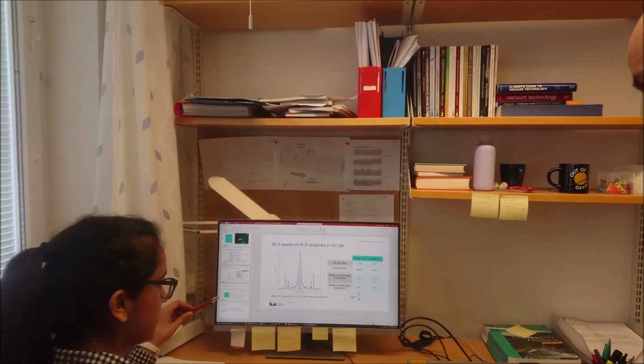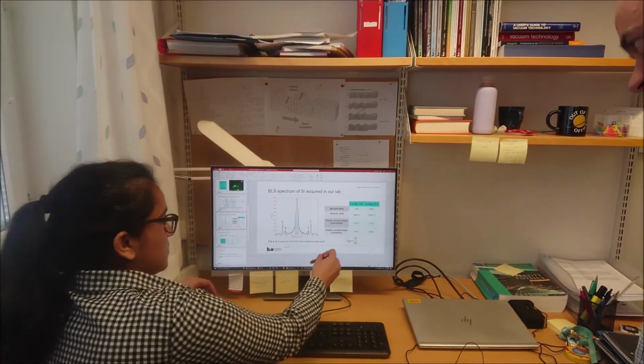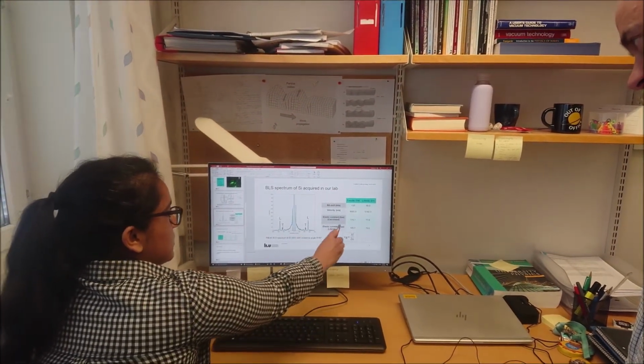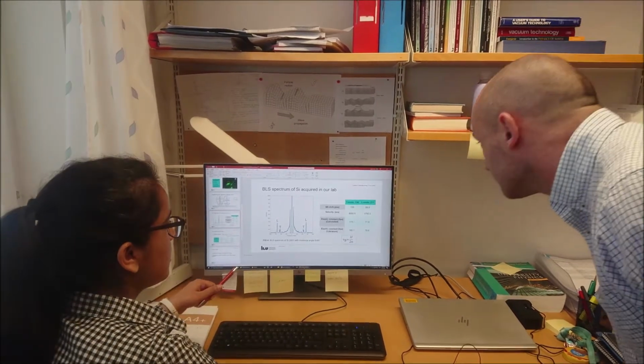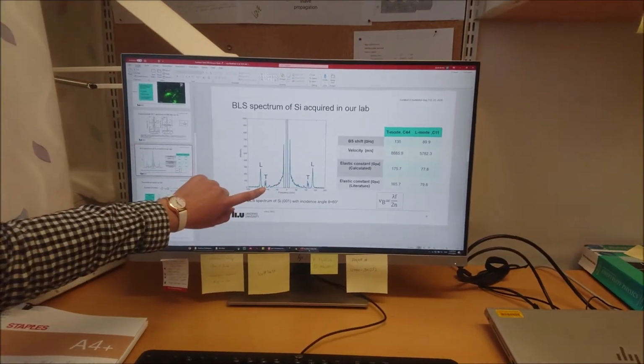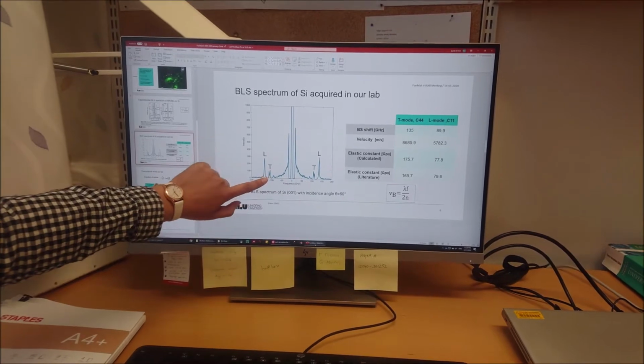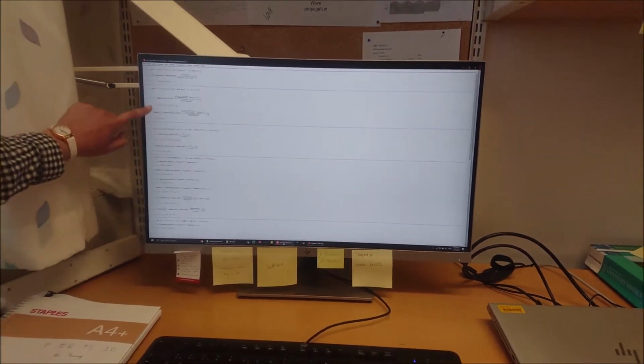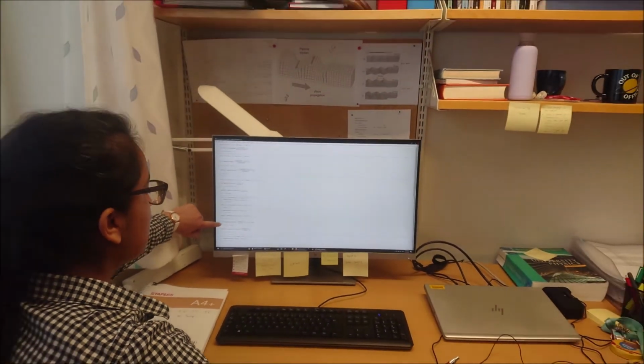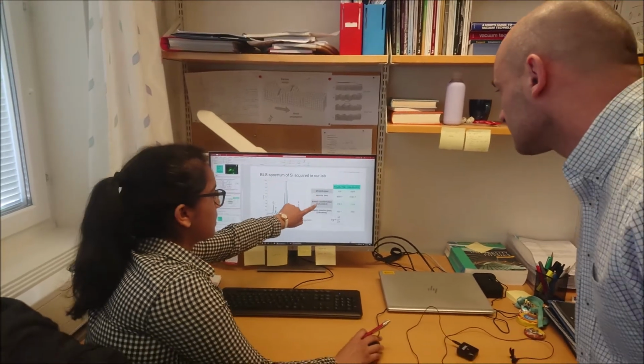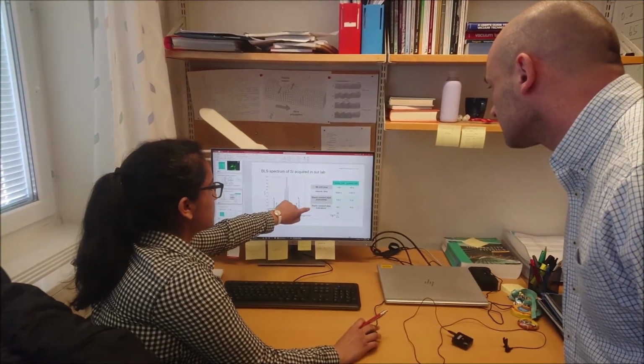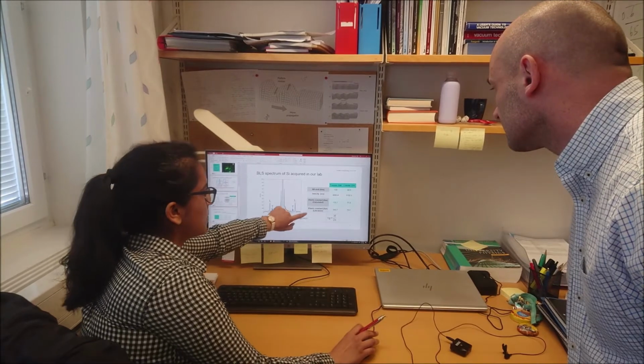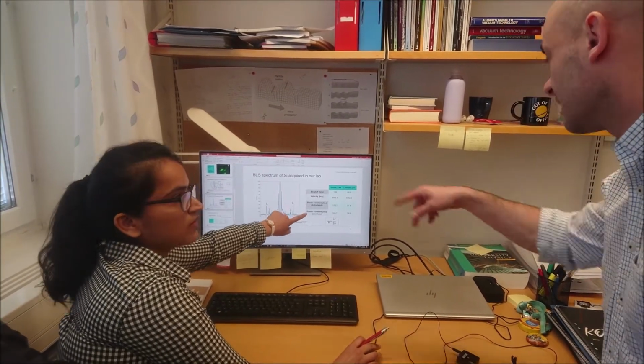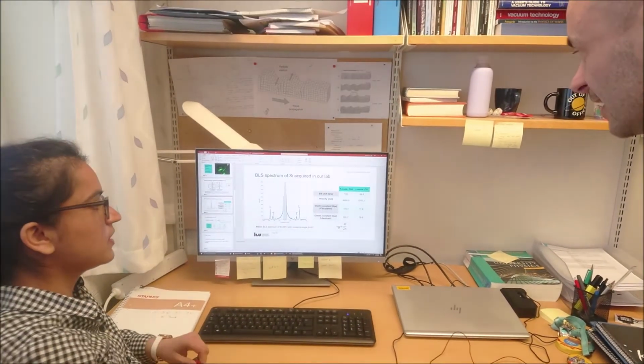Yes, I started with theta equal to 60 degrees, and I calculated the elastic constants. First we extracted the Brillouin shifts from our experiments, and then I did some calculations for the velocity, and eventually I extracted the elastic constants for silicon, C44 and C11, and they agree quite well with the literature values. That's very good. That's promising.